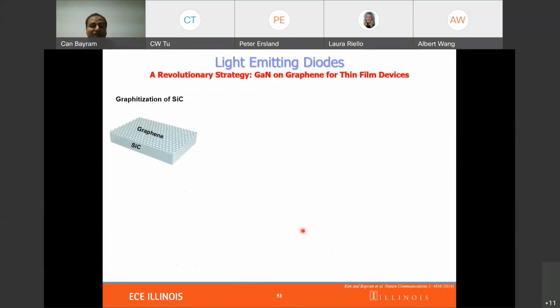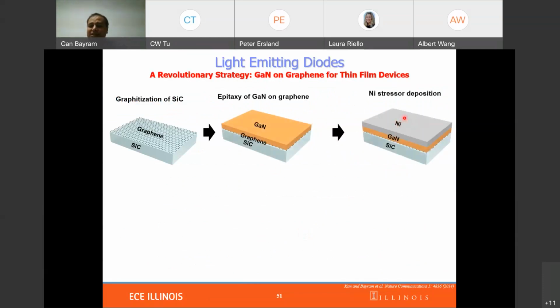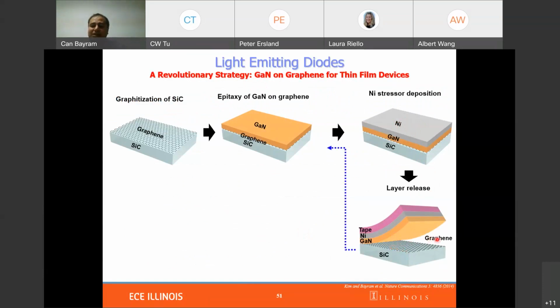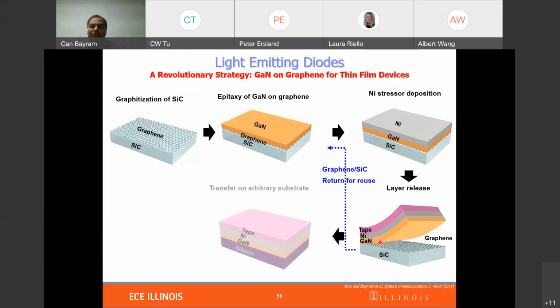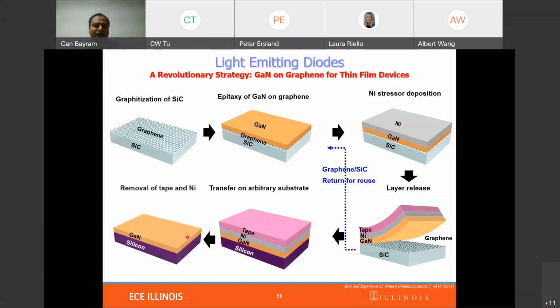and that's where we introduced graphene as a mechanical release structure. What I'm going to show you is the first use of GaN on graphene directly without any buffer layer. We start with graphenization of silicon carbide, and then we deposit gallium nitride atop. Then we use a stressor nickel and a tape to release the gallium nitride from the graphene, and basically graphene stays with the silicon carbide, so you can reuse it infinitely. And for the remaining GaN, because the surface is very smooth, you can just bond it to anything you want. I will show it on silicon, and you can just remove the tape and the stressor layers.